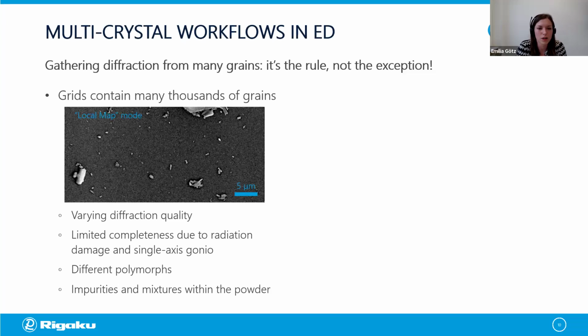There are also other important aspects, which is the limited completeness you can get out of each crystal, especially if it's in a low symmetry space group. You can have different polymorphs or even mixtures of different compounds or impurities in your sample. And so it becomes really important to screen and also collect from a number of crystals and not only a single one.